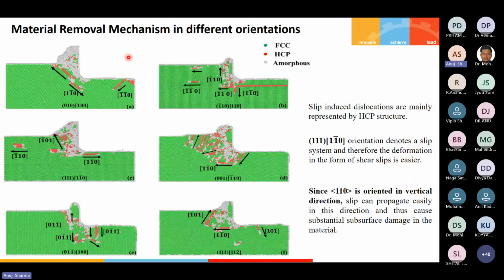What I see is that the slip-induced deformation, the dislocations, mostly took place in the 110 direction, because the 111 plane and 110 direction denote the slip system, meaning shear slip can be formed more easily in this cutting orientation. That's why in the 110 direction, these are most dominant. We can see that most subsurface damage took place in this orientation, where the 110 direction is in the vertical direction. Since 110 is oriented vertically, slip can propagate easily in this direction, and thus substantial subsurface damage can occur.